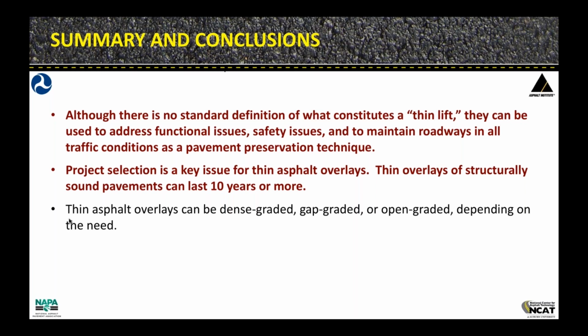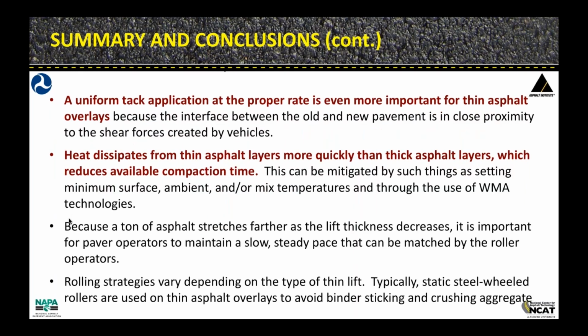Again, these thin asphalt layers can be dense graded, which tends to be the most popular, but they can also be gap graded or the open graded friction courses. Tack coat application, again, is very, very important at the right rate, but it also has to be consistent, both transversely and longitudinally, and we have to make sure the tack coat stays there, that it doesn't get picked up by the construction vehicles. The time for compaction is greatly reduced for these thin layers. So again, have to be aware of that and make sure that the paver doesn't get too far out ahead, and get away from the urge to go too fast. Rolling strategies, again, are typically going to be, for the most part, steel drum rollers in static mode, whether it's the dense graded mixes versus SMAs or open graded friction courses.